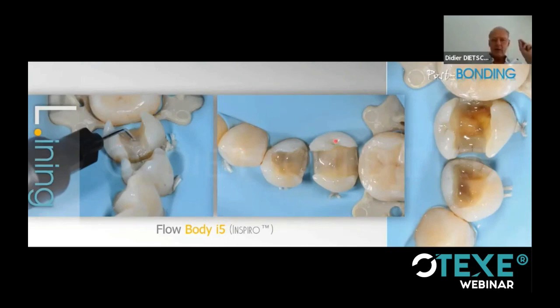Now, you look here. This is the cavity without the liner. This is the cavity with the liner. It's about 1 millimeter, 1.5 millimeter maximum. Understand that if you create too much flexibility by adding a lot of flow, you get a counterproductive effect. You get too much deformation, and in turn, it will even create a less favorable situation.